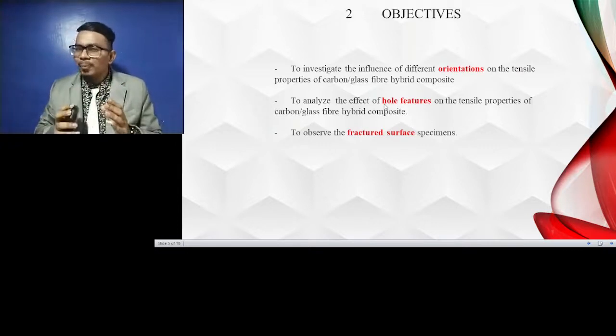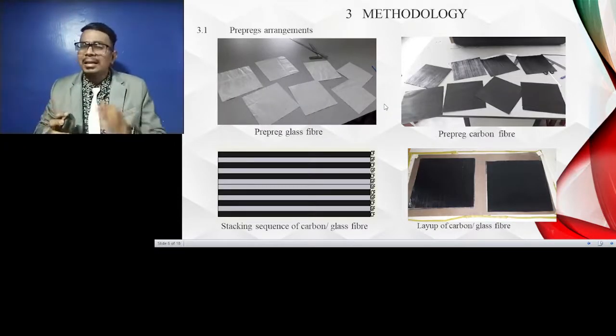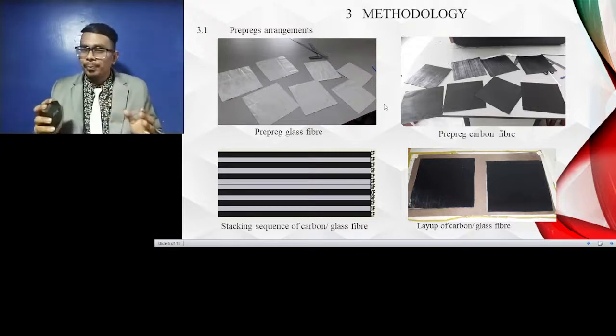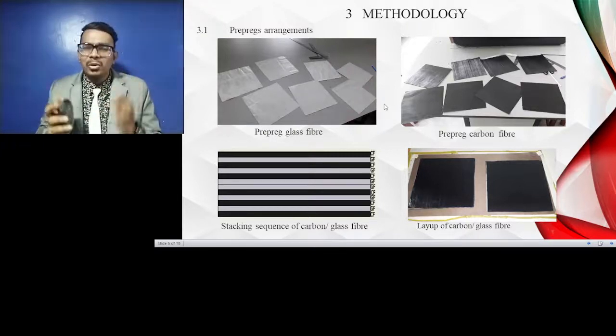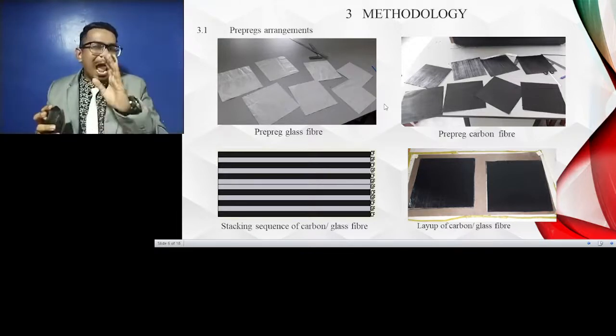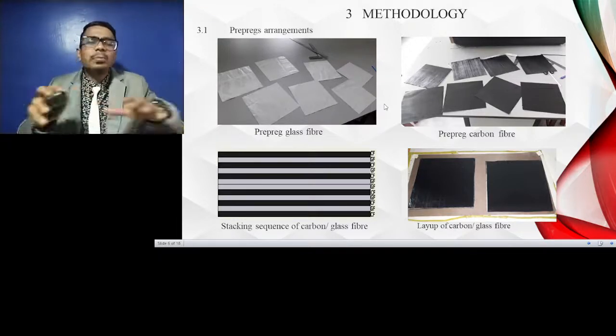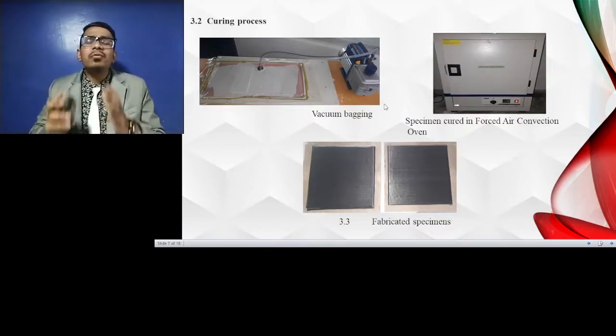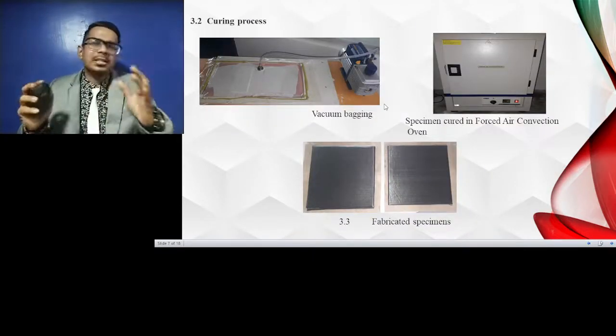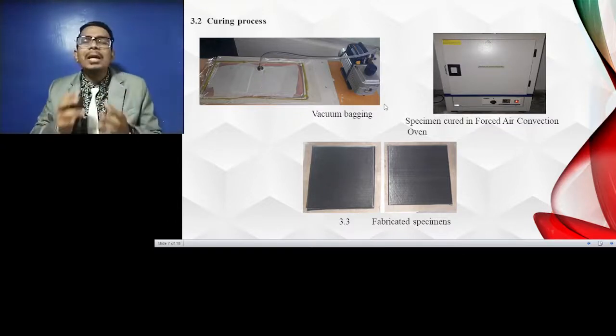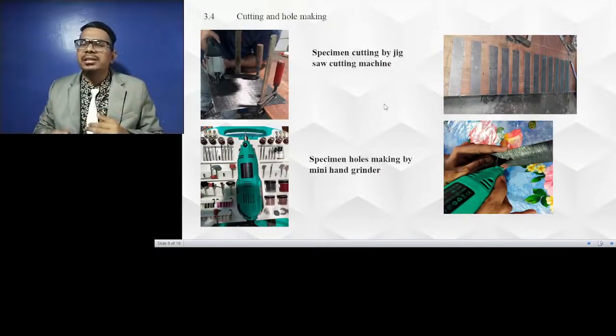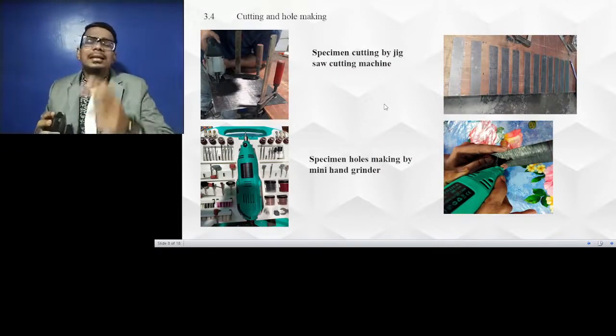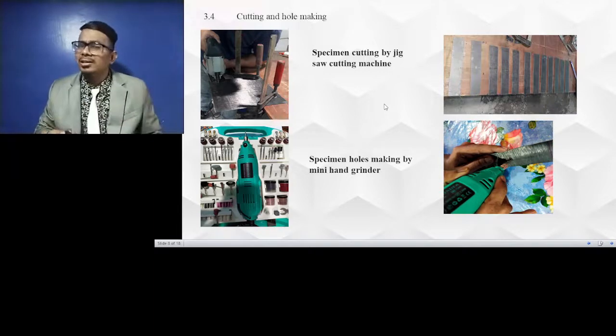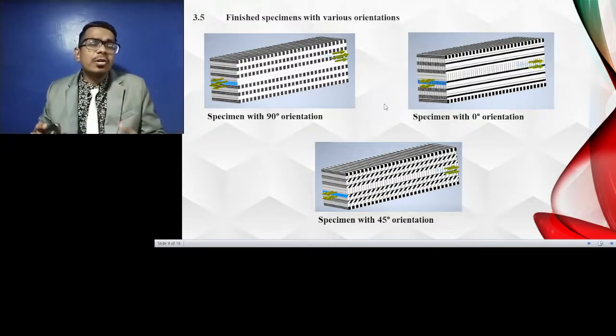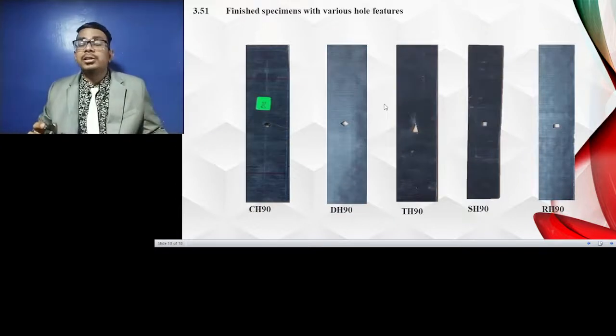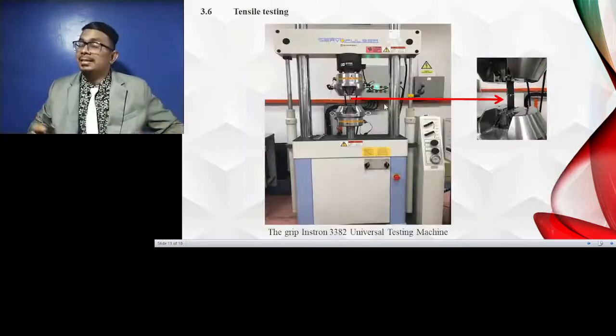Now, let me look at the methodology. Initially, the prepreg carbon and prepreg glass were cut and laid up on the aluminium plate based on the required orientations using the hand layup method. Followed by that, the prepreg laminates were cured using vacuum bagging and a forced air convection oven. Once the specimens were prepared, they were cut using a jigsaw cutting machine. Then various holes such as circular, diamond, triangular, rectangular, and square holes were made. These images show the various orientations and holes which have been used. Then the tensile test was carried out.